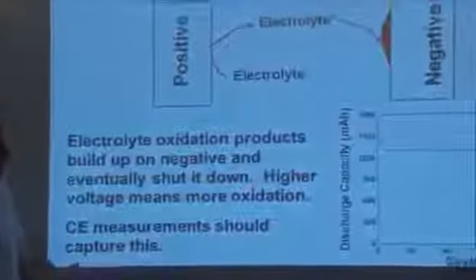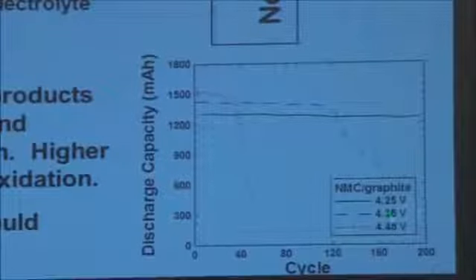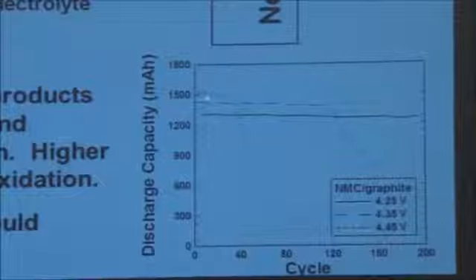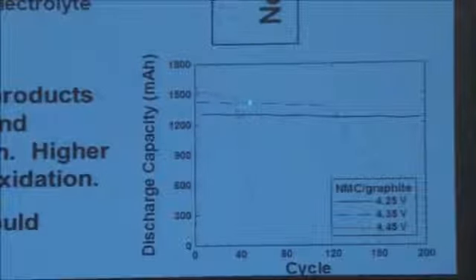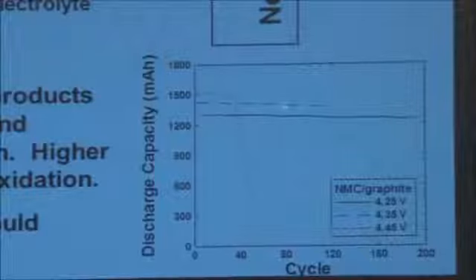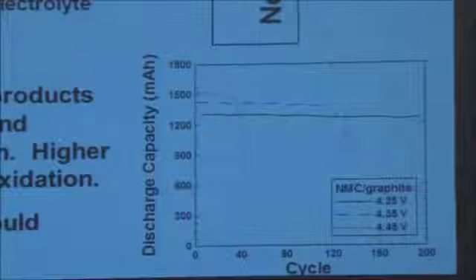Now here comes the ultimate challenge for this method. And that is that sometimes lithium-ion cells show this kind of failure that's incredibly insidious. So these are nickel manganese cobalt positive electrodes with graphite negatives. Cells are cycling to an upper cutoff of 4.25 volts, and they look really, really good. And if you change the upper cutoff voltage to 4.35 volts, they start out looking really, really good. Imagine this was in your car. You'd say, oh, everything's great. I love it. Then all of a sudden you can't even get out of the driveway.